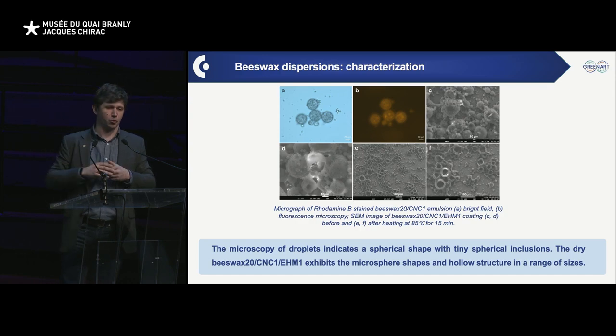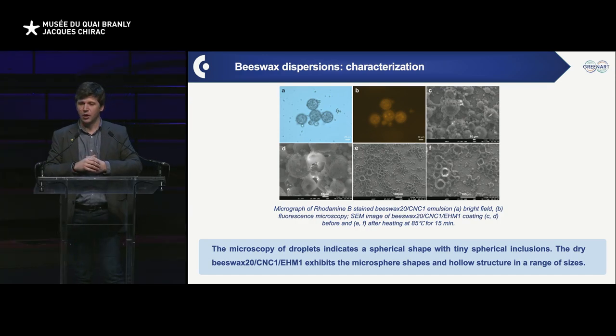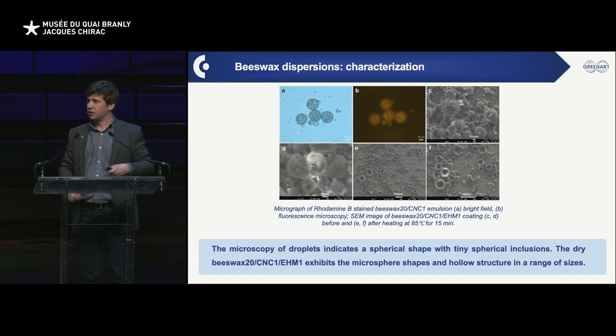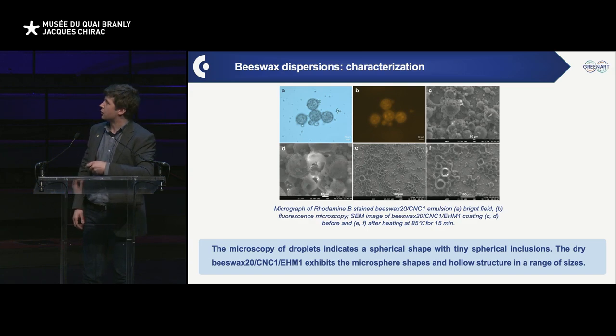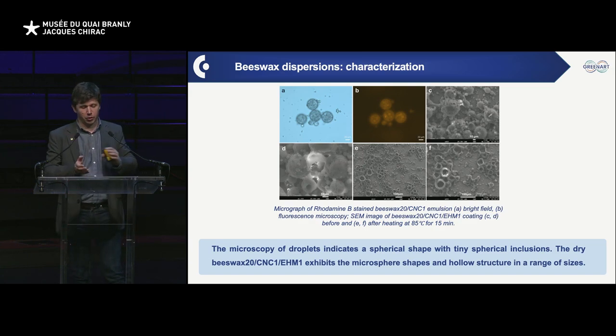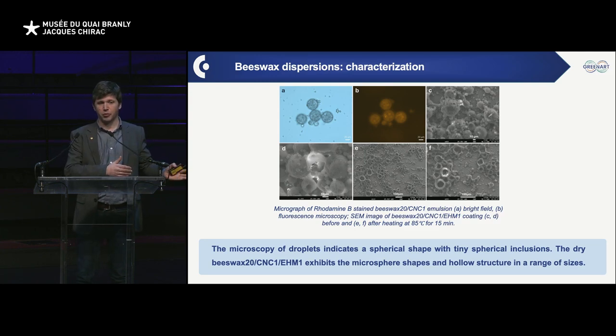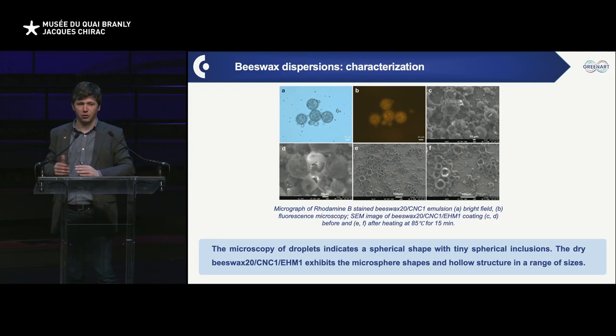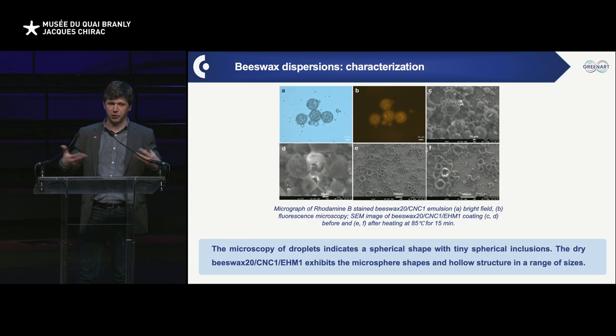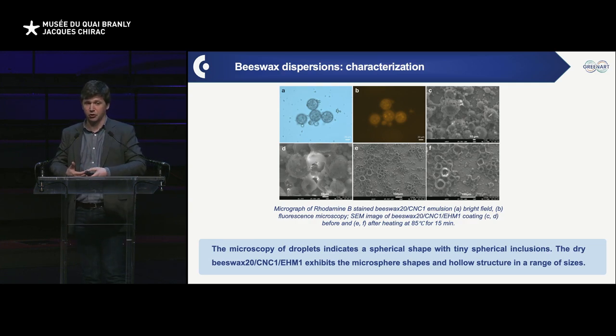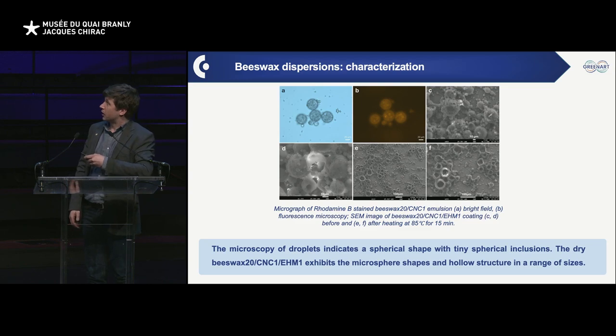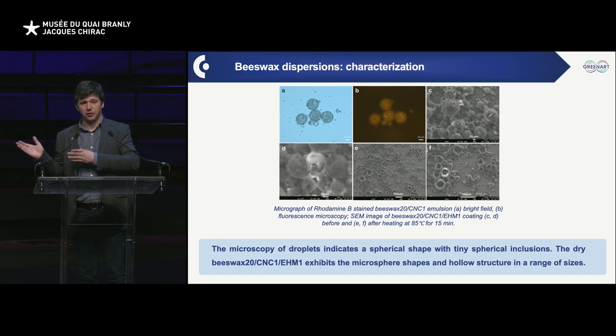With optical microscopy, we cannot see the nanocellulose, it's too small, but still, we didn't expect this kind of inclusion and this type of void that we could see here. And that means there is a double emulsification process going on that comes from the beeswax that has probably slightly hydrolyzed along the way, so it gets to be surface active. There are some free fatty acids that help in the emulsification. But then we make emulsions that potentially have a void in the middle when they dry, when they crack. And that is not a bad thing, because that will enable some breathability of the system.